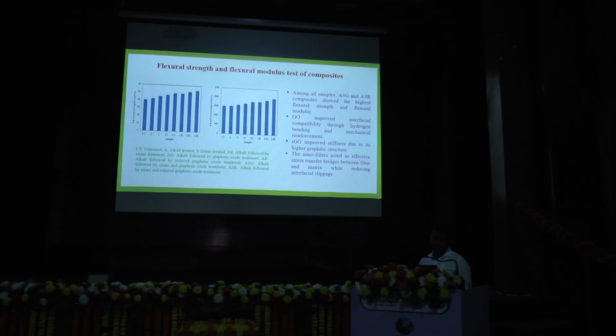The next is the flexural strength and flexural modulus test of the composite. Among all samples, the ASG and ASR composites show the highest flexural strength and flexural modulus. GO improved the interfacial compatibility through hydrogen bonding and mechanical reinforcement also. And RGO improved the stiffness due to its higher graphitic structure. And the nanofibers act as an effective stress transfer bridge between the fiber and the matrix while reducing the interfacial slippage. And we see the same trend as the increased tensile strength in ASG and ASR samples.